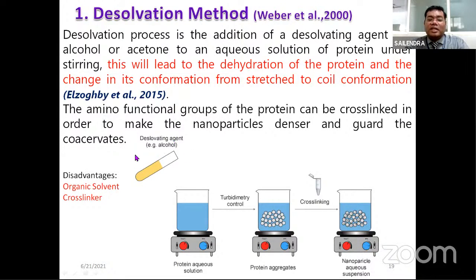Immediately, you are going to add the desolvating agent. The desolvating agent is your alcohol. Now, it is not that you take the test tube and simply pour its contents into this solution, and immediately the nanoparticle is going to precipitate, and you add the cross-linker and get the nanoparticles. It is not like that. You will take this desolvating agent and add it drop by drop. Now, what apparatus do we have where we can give this alcohol drop by drop? Because this alcohol has a very low surface tension and it can immediately vanish from the tip itself. So always use syringes. 1 ml syringes, like those used for insulin injection, can be used. You can use pipette tips that release 1 microliter, micropipettes, also for dropping this alcohol. And while the protein is stirring at the bottom, you have to add this alcohol drop by drop.